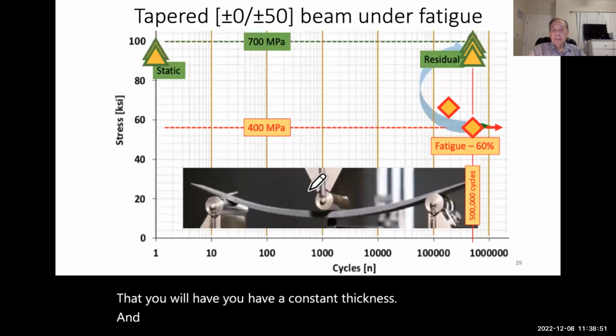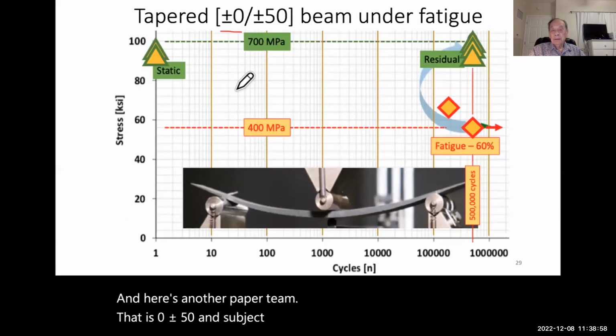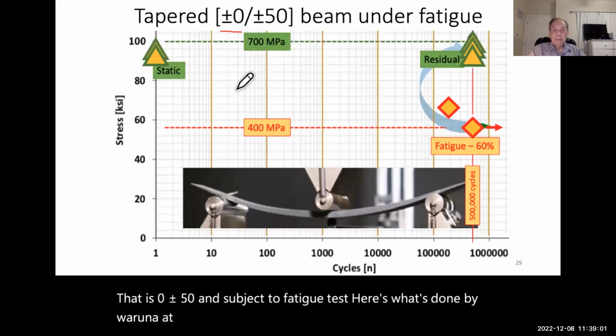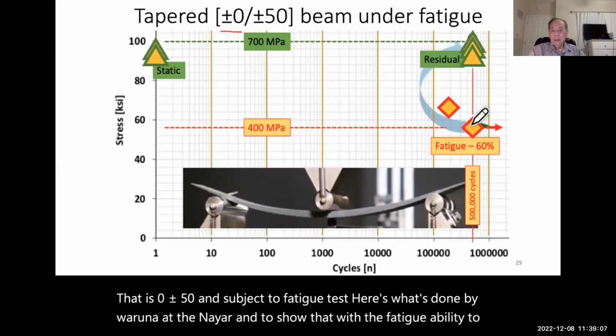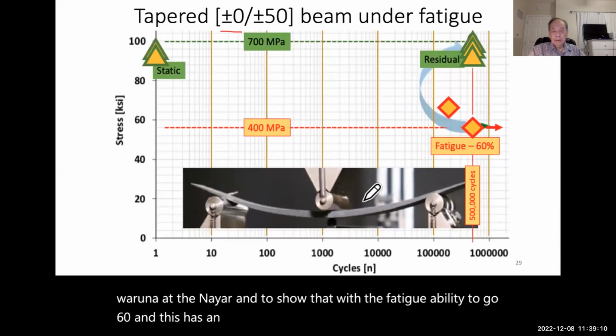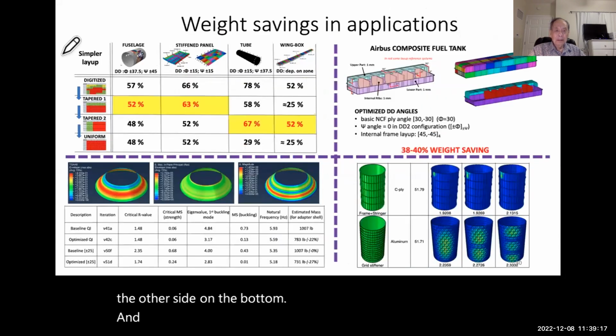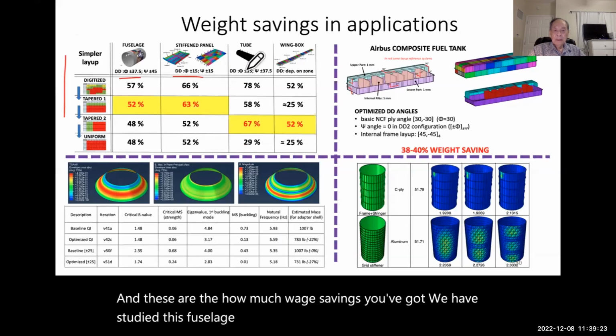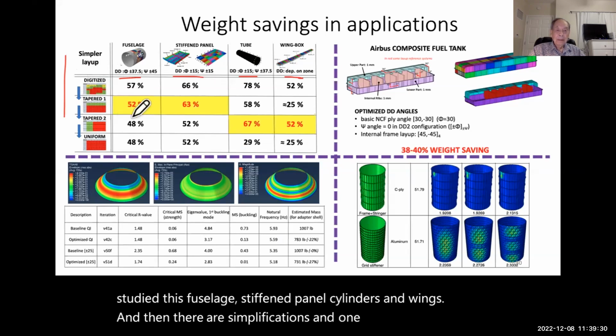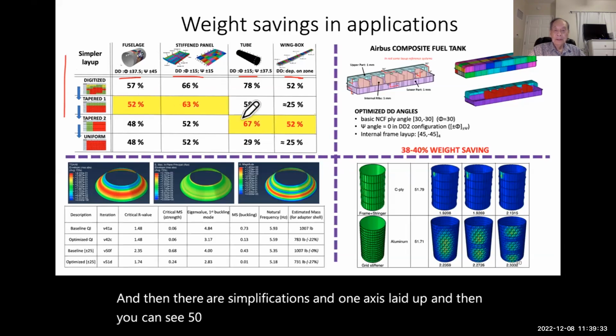And here's another tapered beam that is 0 plus or minus 50 and subject to a fatigue test. This was done by Varuna at the NIAR. And to show that with the fatigue, its ability to go 60%. And this has the external plate drops, on one side on the top, and the other side on the bottom. And these are how much weight savings you have. We have studied this fuselage, stiffened panel, cylinders, and wings. And then there are simplifications of one axis layup. And then you can see 52, 63, 67, and 52. These are percentages of weight savings.